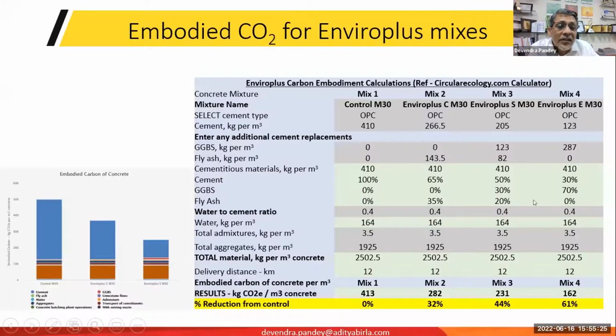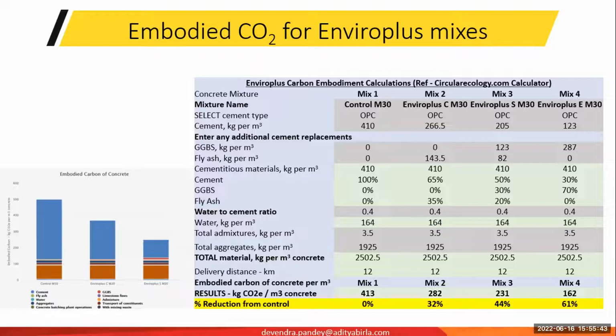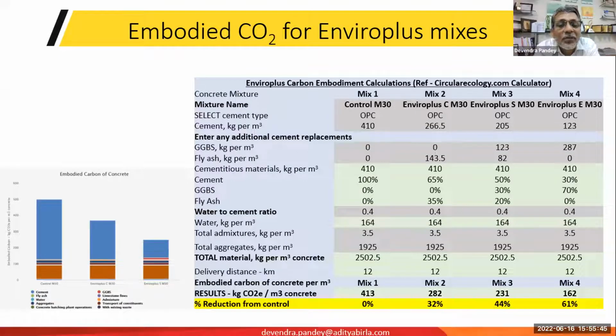How is this done? So here we go. I'm showing you here four mixes. Mix one is basically if we made an M30 grade concrete using just OPC. It would consume about 410 kgs of OPC, and the CO2 footprint per cubic meter of concrete only for material production. I mean, we can, of course, extend this analysis right up to construction and even the life cycle. But at the moment, I'm covering the material.